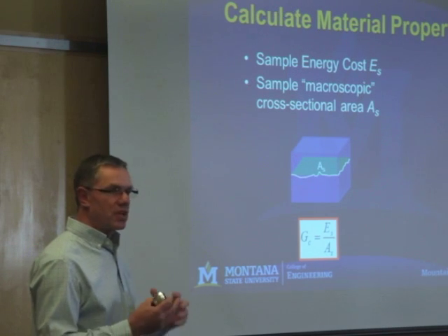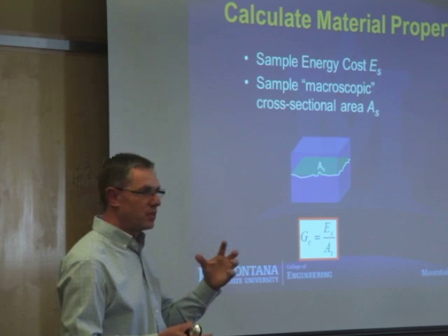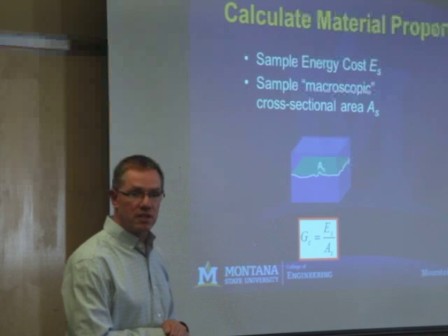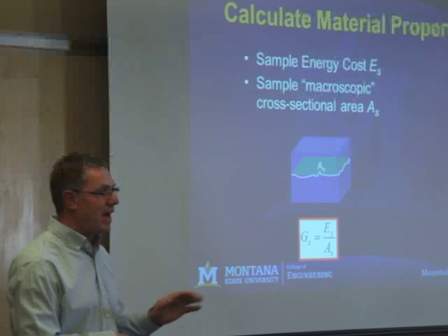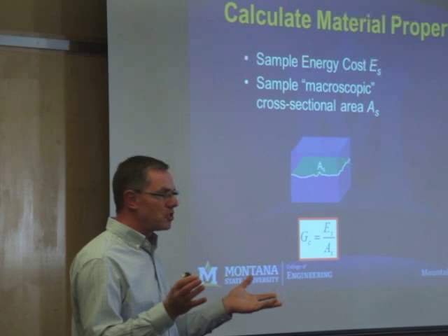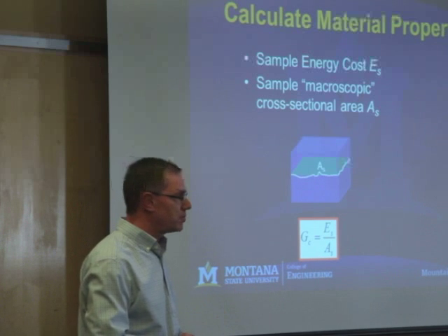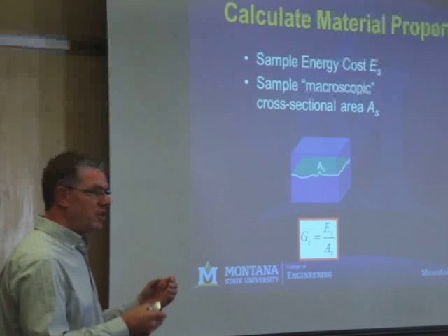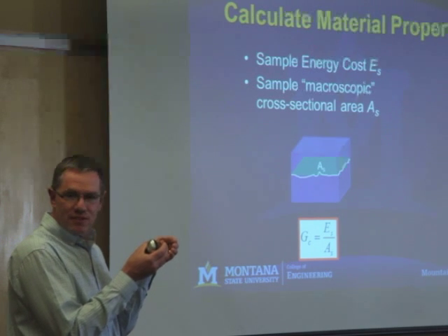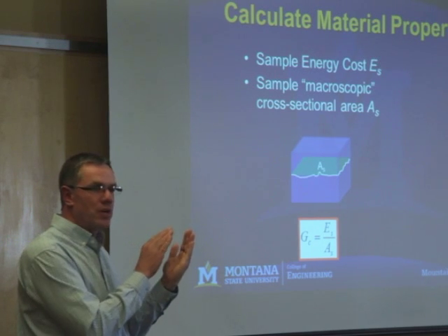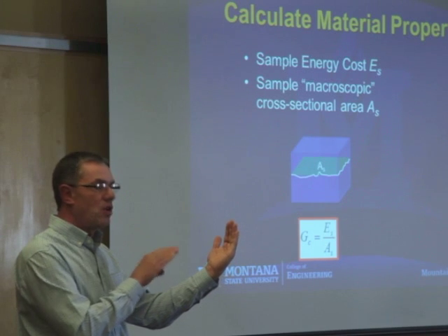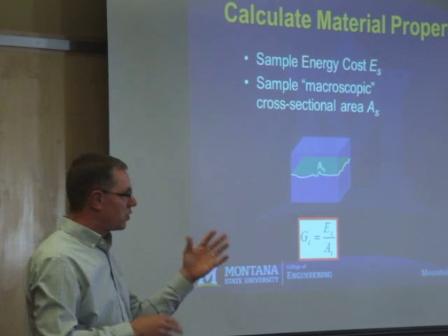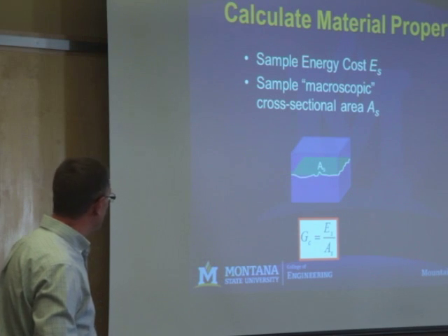But we all know that things like microcracks happen, right? We get a little bit of cracking that goes off that doesn't result in the main path of the fracture. Sometimes called strain softening. If you're reading the literature, sometimes microcracking is what they call strain softening. And so we've got a way of doing that. We just look a little bit ahead, right? We take a little volume, look ahead, where would a crack go, then we open that volume and find out, oh, that original path wasn't the path it wants to take now, there's another one. And so we're finding ways where we can simulate microcracking with this.